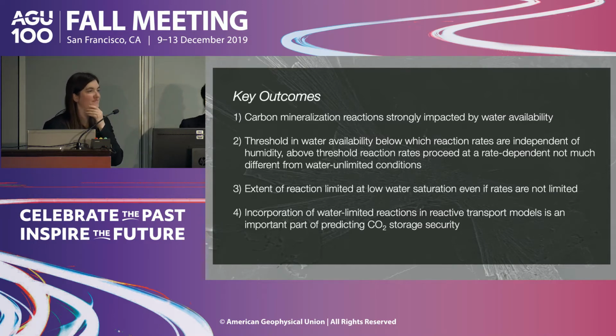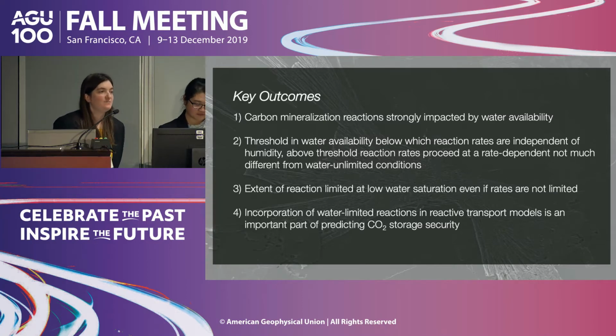Do you know which magnesium carbonate you have? Good question. It's most likely dypingite. So we identified them with infrared spectroscopy, but the spectra for dypingite and hydromagnesite are almost identical. So we don't know for sure whether it's one or the other, but usually under these low temperature conditions, it's more likely to be dypingite, and based on the morphology.